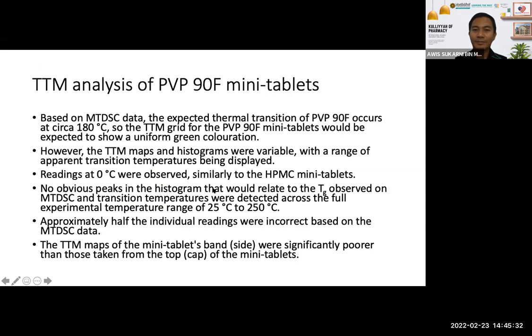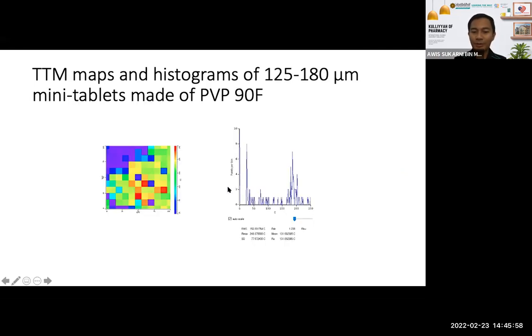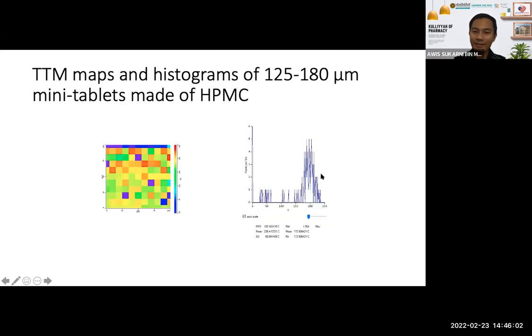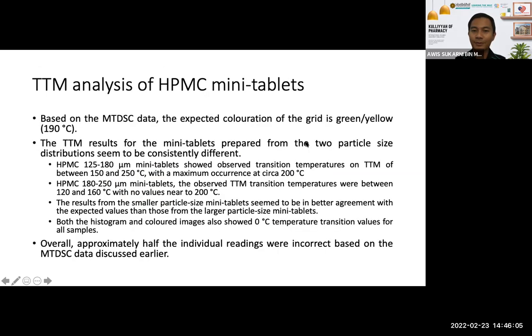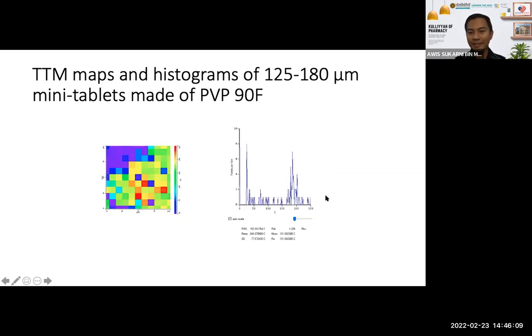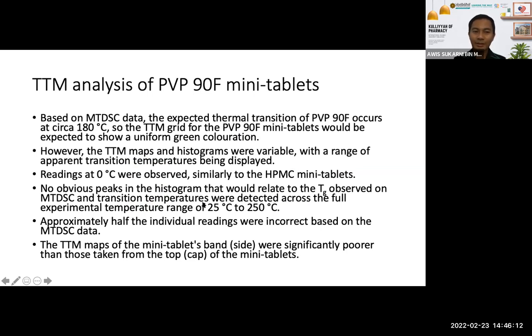So again, we expect it should show a green color, because based on the MTDSC, the transition temperature is around 180 degrees. And similar to the HPMC, we notice there are 0 degree readings as well, and there is no obvious peak on the histogram. It's quite scattered compared to the previous one, which focused on one area. The PVP is quite scattered, and approximately half of the readings were incorrect based on the MTDSC data. It means they're not near 180 degrees.